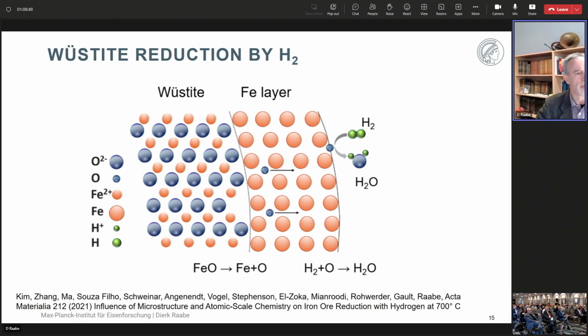Now, once you have formed the iron layer, you form a chemical potential gradient between that surface and the inner interface between wüstite and iron layer, so that the iron oxide, the oxygen ion, must leave behind 2 electrons, reducing locally the iron. Then this oxygen atom diffuses outbound following the chemical potential gradient to the next nearest surface. It doesn't have to be a free surface, very important. And the iron is reduced, relaxing on the inside so that the iron layer grows towards the inside. So that's the elementary ionic transport conditions here.